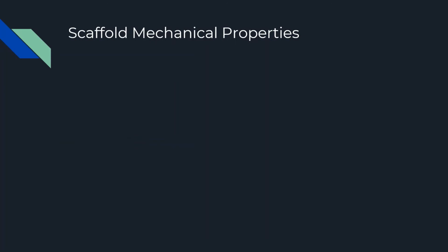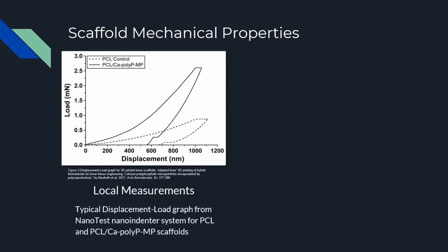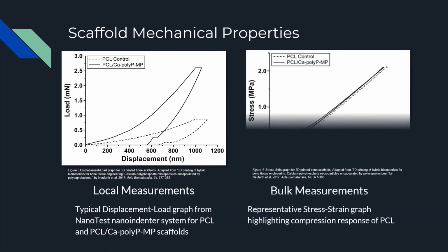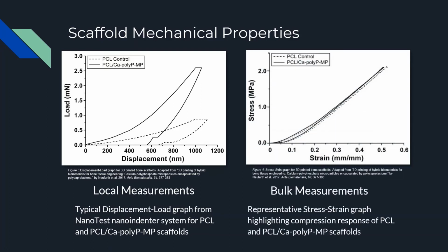Both local and bulk mechanical properties were tested for the PCl and PCl calcium poly-P scaffolds. Using a nanotest nanoindenter system, the researchers found a 119.2% increase in Young's modulus, determined by the slope of the displacement load diagram, and an increase of 225.8% in Martin's hardness of the PCl calcium poly-P scaffold compared to the PCl scaffold. For bulk properties, both scaffolds exhibited similar measurements.